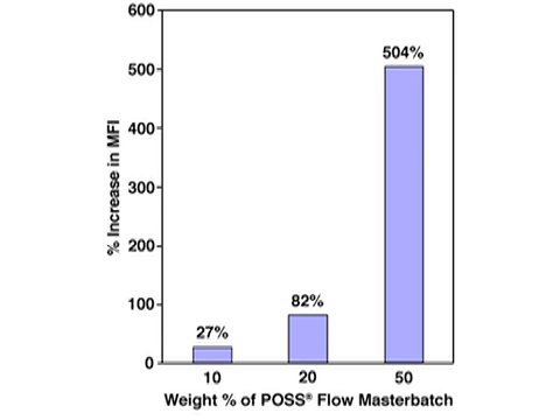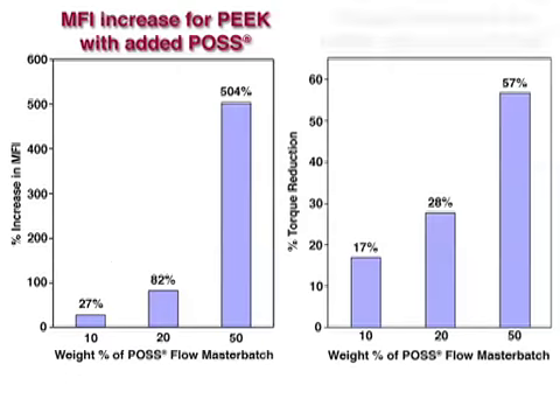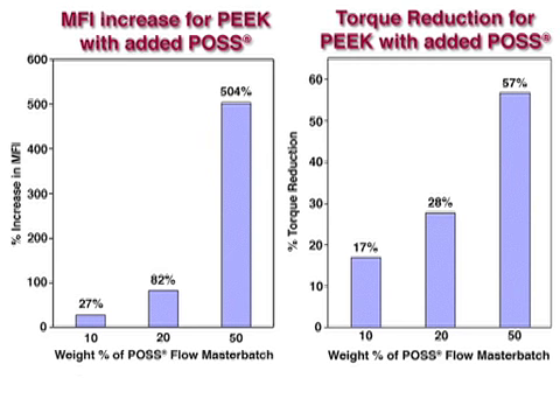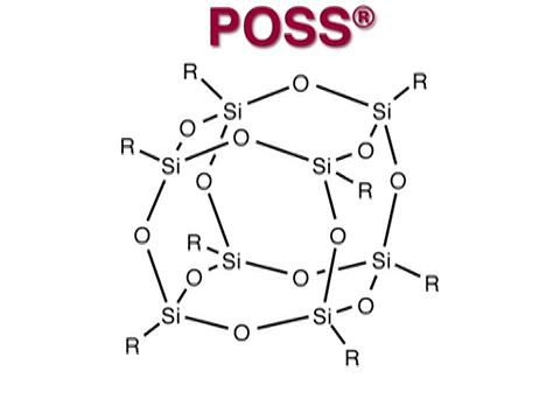These amounts can greatly improve melt flow. Improved melt flow will help reduce extruder torque and therefore processing costs. And POSS is a nano reinforcement and will not give any appreciable decrease in mechanical properties to over 50 weight% incorporation. POSS is a nano reinforcement that can improve the flow of even the most difficult to process materials, including polyphenylene oxide, polyphenylene sulfide, fluorinated ethylene propylene, and Torlon.